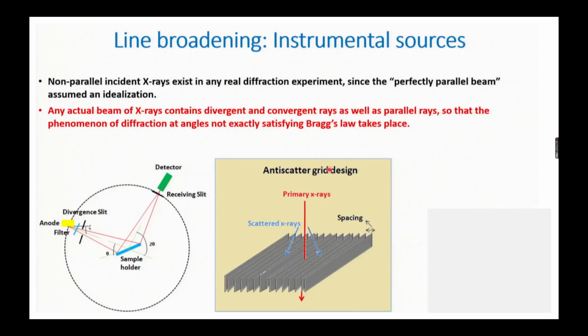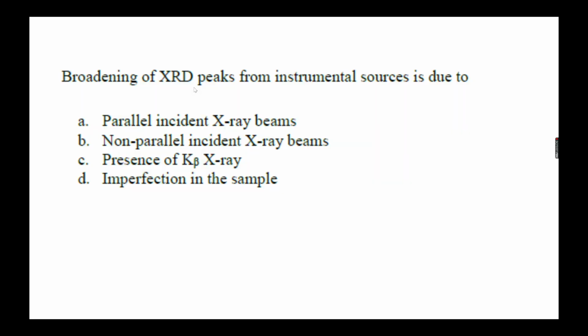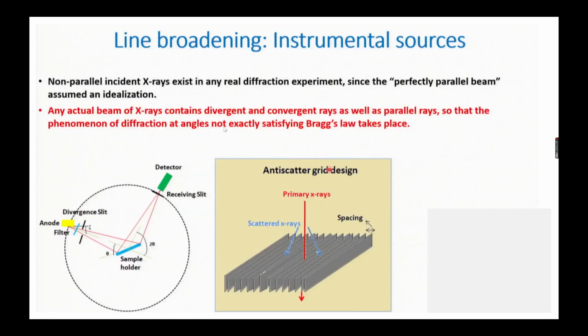So in the line broadening due to the instrumental source, the non-parallel incident X-ray exists in any real diffraction experiment, since a perfectly parallel beam is assumed only as an idealization. So the main thing is non-parallel incident X-ray beams, because parallel incident X-ray beams are assumed just for idealization. It will not really exist, right? An actual beam of X-rays contains divergent and convergent rays as well as parallel rays, so that the phenomenon of diffraction at angles not exactly satisfying Bragg's law takes place.